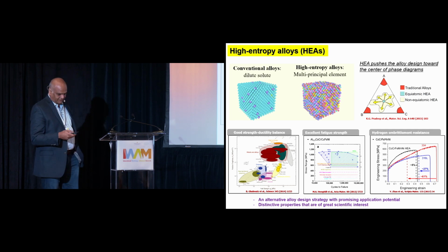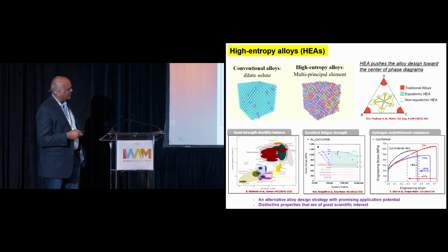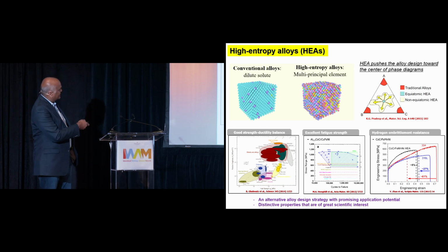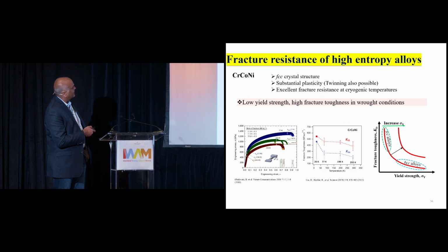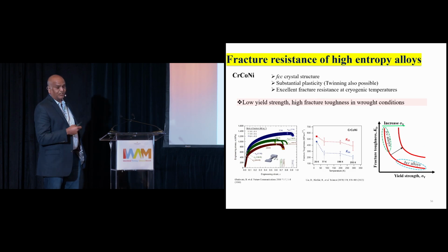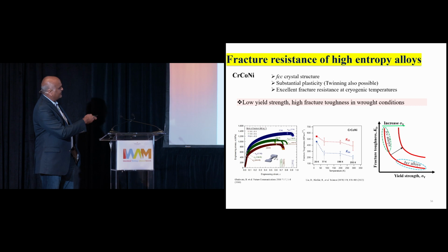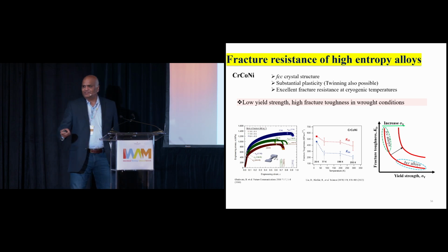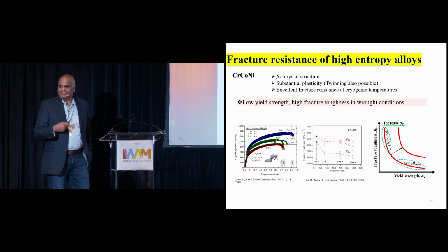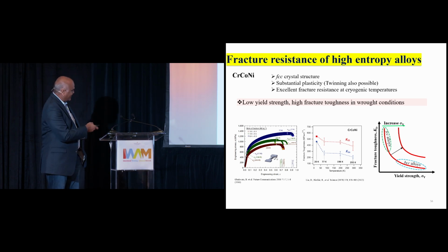These alloys seem to have caught the fascination of the metallurgical community because they have interesting mechanical properties, including a good strength-ductility balance, and in terms of hydrogen embrittlement resistance they seem very good. This is not our work, it's Rob Ritchie's work, but these alloys seem to have world record fracture toughness numbers—around 500 MPa√m, especially at very low temperatures, whereas steels will have maybe not even 100. That's how they got into Nature papers. FCC-based ones have the issue of not much strength, but very high fracture toughness.